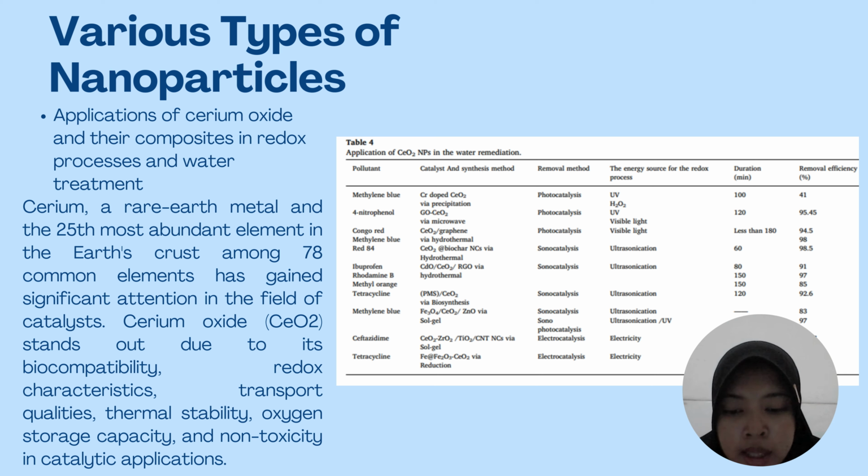Cerium oxide possesses several appealing attributes including the presence of empty 4f orbitals that facilitate electron transfer, high stability in reaction environment, notable oxygen mobility resulting from the reversible transformation, and the ability to form a continuum of oxygen non-stoichiometric compounds.